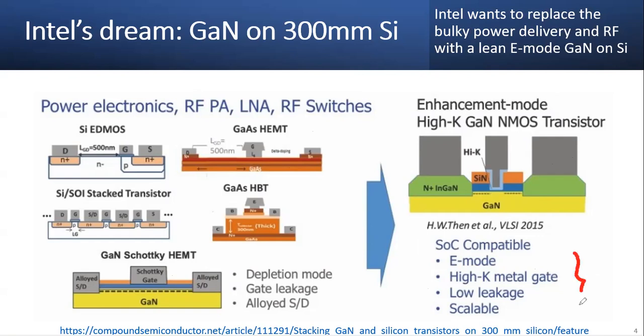Of course, they use their process technology expertise in this field. They could use work function metal to tune the gallium nitride, which is a naturally depleted device, into an enhanced mode, which is VT greater than 0. And that will be the goal of this device. And high-K metal gate, Intel invented this process, and to lower leakage and be scalable, they want to put it onto a 300 millimeter silicon. They want to replace this bulky, everything separate, into one package, one device per se.